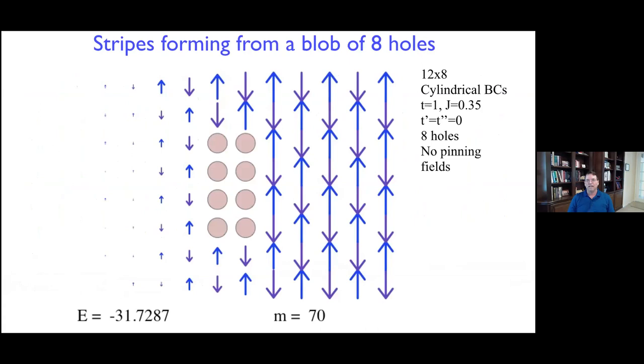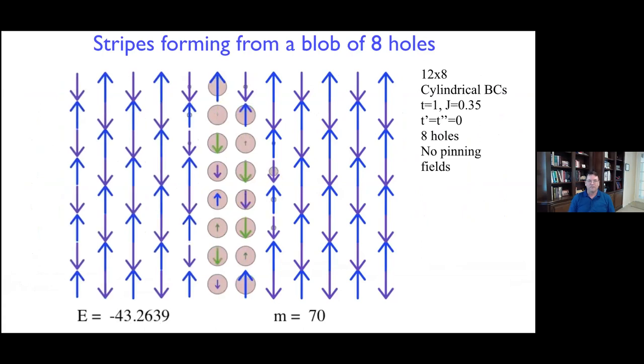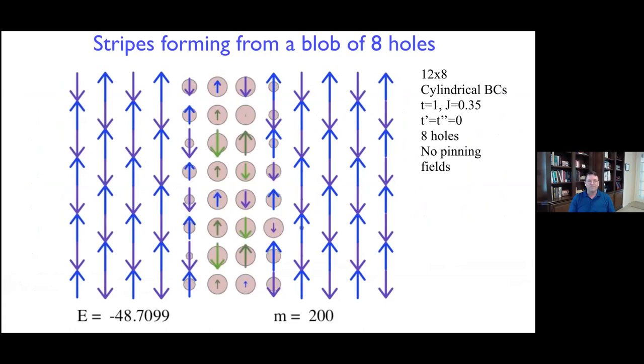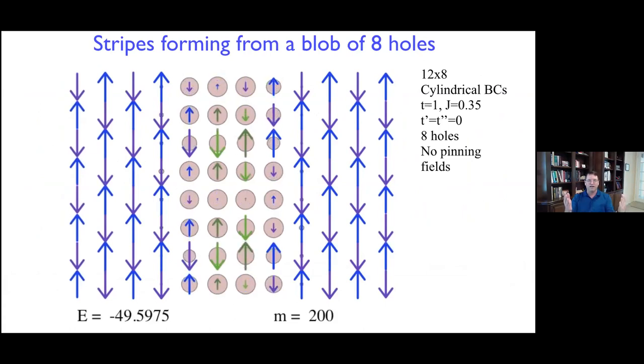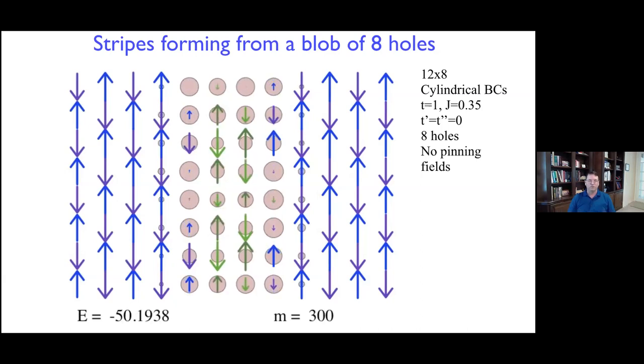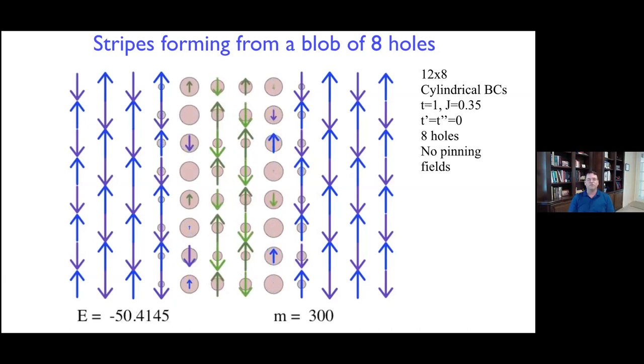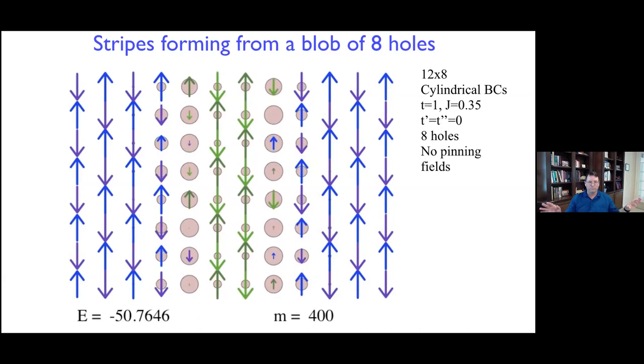So this case has T prime equals zero, and 8 holes are put in. This is just about the beginning of the run, where these 8 holes are sitting in the center of the system. We let it run, DMRG sweeping, energy goes down, and we see what the system wants to do. It immediately spreads out because it wants the kinetic energy of the holes, and then starts getting some more structure to it. It doesn't just spread out into a uniform blob, you can see stripes forming.